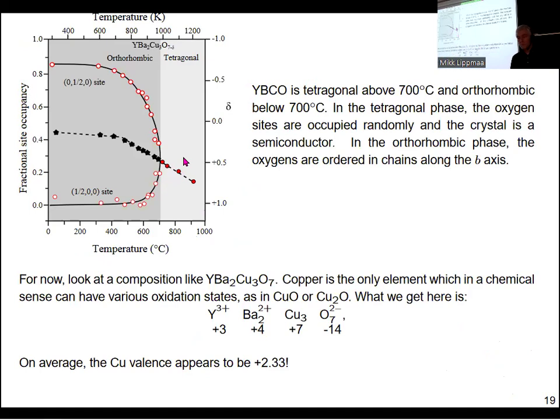Now, if you are clever, you set your furnace to cool very slowly. And originally, when making these materials, people just discovered that if they just switch their furnace off and wait until it cools slowly, then what they get is not a green material, but a black material. And you measure X-ray diffraction, and A and B axis directions are different, so it's orthorhombic, and it's superconducting. And if you do careful oxygen location analysis, for example, by neutron diffraction, then what is apparent is that if you cool very, very slowly from high temperature, then at around 700 degrees, the crystal starts to change, and the fractional occupancy at the A-axis site goes down to 0. So the A-axis sites are these.